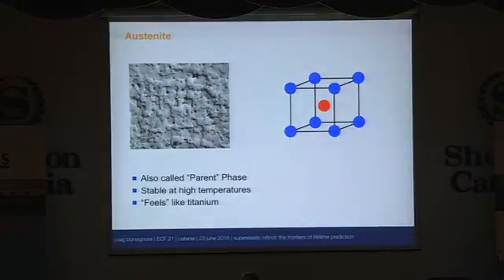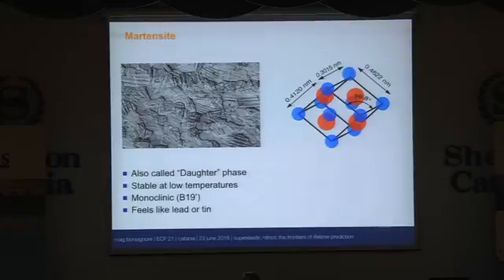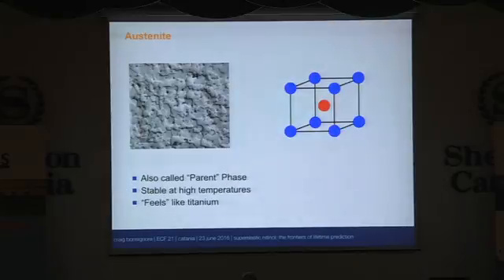The material does have a phase change that it goes through, and there are two primary protagonists here, and there are some others that I'll gloss over. But we deal with austenite, which is the high temperature phase of the material. It feels like titanium. It's kind of stiff and strong. We'll call that the parent phase. And then martensite, which we'll call the daughter phase, is a lower temperature phase. Feels like lead or tin. It's a soft material. And the phase transformation basically cycles between these two crystal structures.